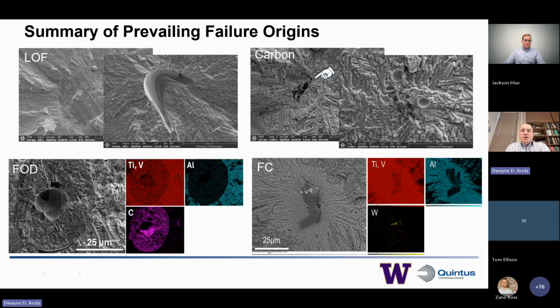What I'd like to do, though, is just make sure I point out the kinds of things that we see with regards to the major categories of failure origins from fractography. So for the stress relief condition, we saw voids, either gas pores, which were largely circular in shape with an aspect ratio close to 1, or we saw much more lack of fusion voids.